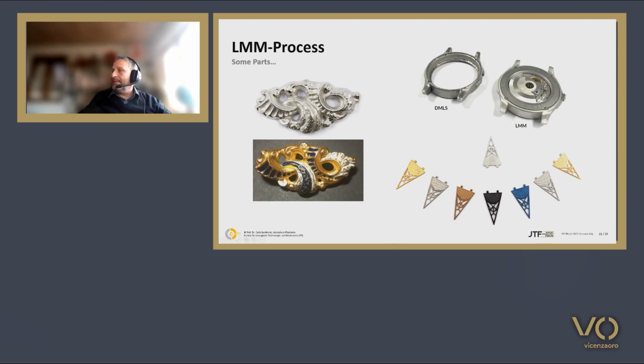On the right side, always the same part. Here, on the left side, electroplated with gold. All the others are PVD coated in different colors. And just for a comparison, a DMLS part that has been reworked for 3 hours. And you see here where the support structures have been to support the material. On the right side, the same watch case as printed and fitted into the watch case.